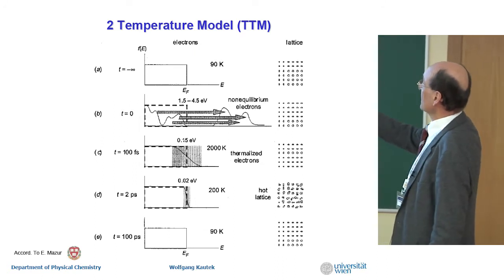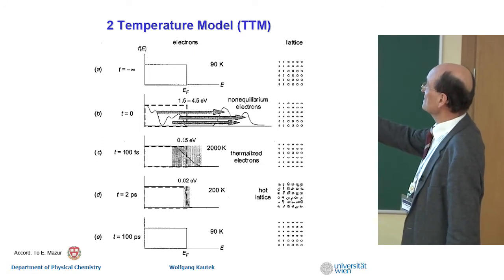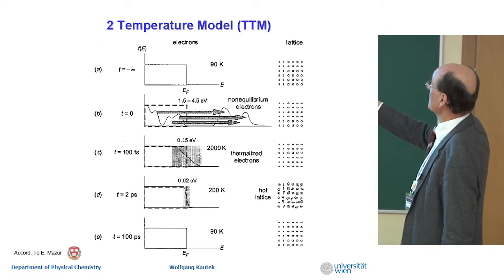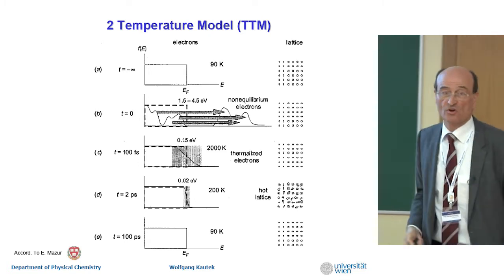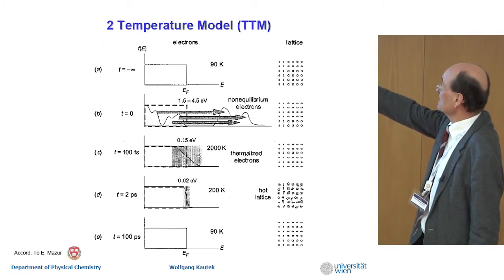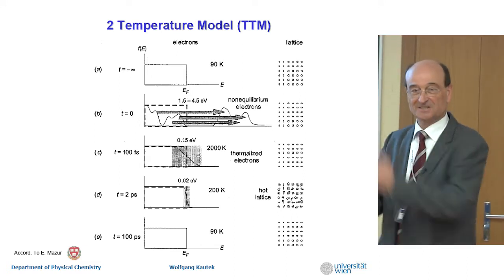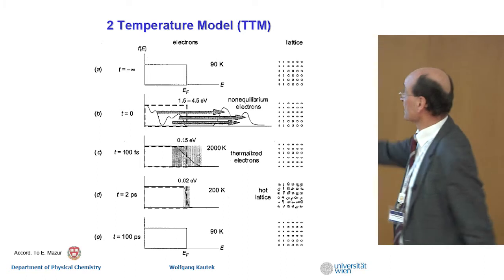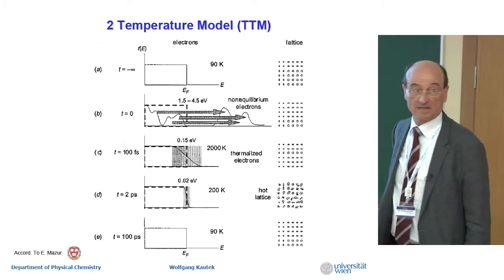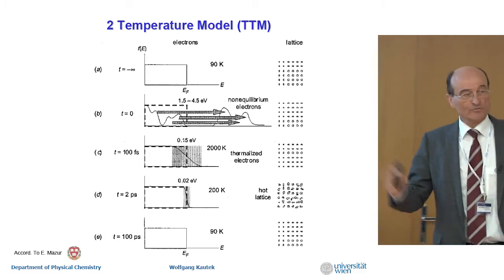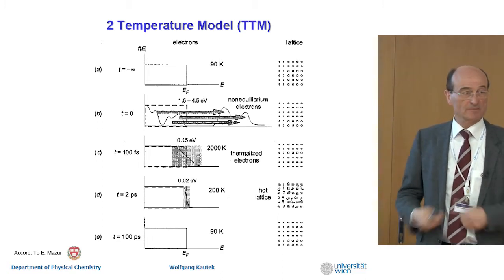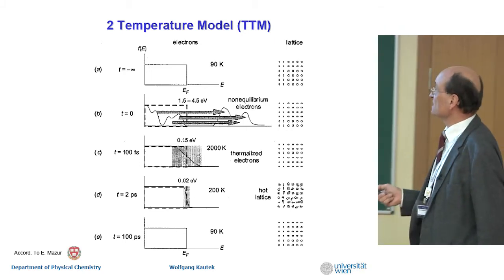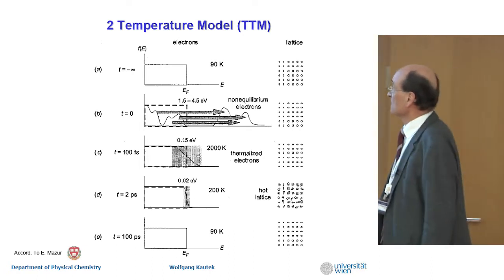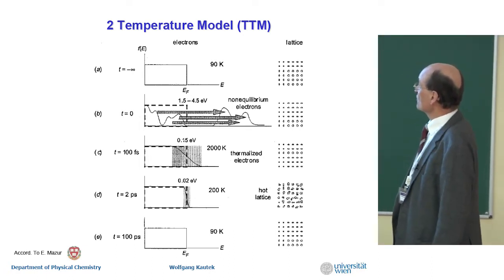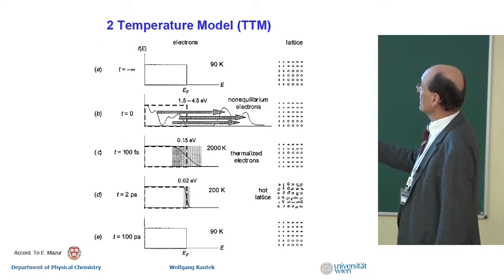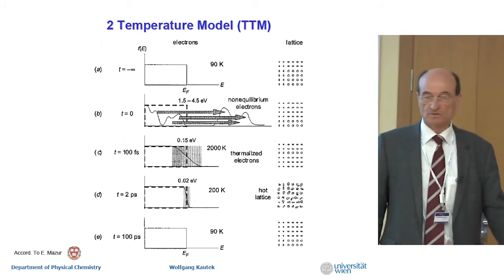There are the balances between the electrons here. This is the heat capacity, diffusion term, the generation term, and the dissipation term. This dissipation G here is the generation term for the lattice heating. What the electrons are dissipating to the lattice is the generation term in the lattice balance. Now that's the so-called two-temperature model, and to a first-order approximation, this is a very dependable approach to describe the interaction of ultra-short pulses with metals. And here is the border between non-thermal and thermal, and then in the long run you can describe it with the classical heat diffusion equation.